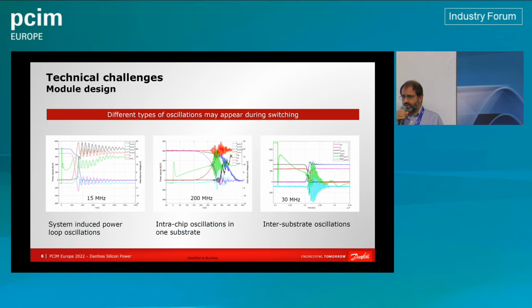But then there are at least 2 other types of oscillations that we see. One is the so-called intra-chip oscillations, or intra-substrate oscillations, which take place due to the bonding structure and the different inductance of each of the chips, and the interplay with the transconductance of the chip. In essence this is working as a feedback system with positive gain, and if you do not keep the real part of the eigenvalues of the system under control, then you can get this type of oscillation. So that's something you have to be careful of.